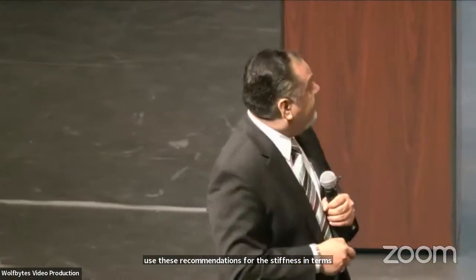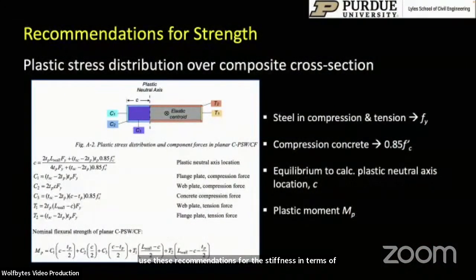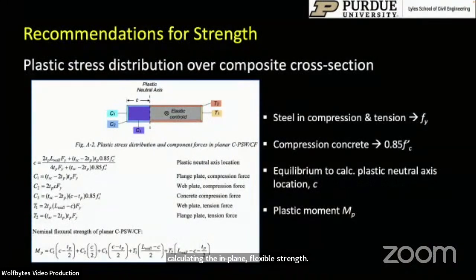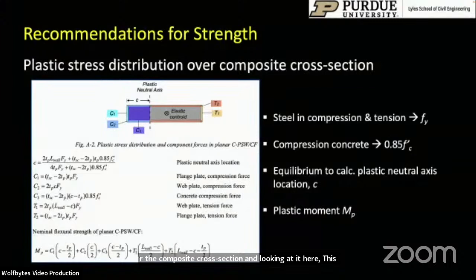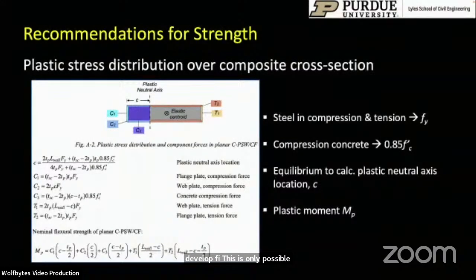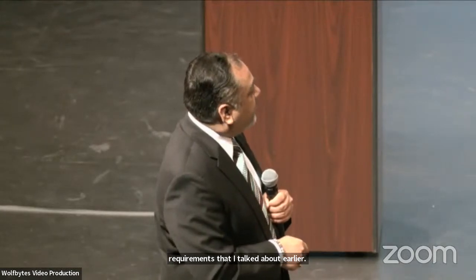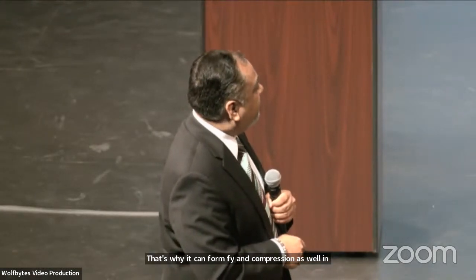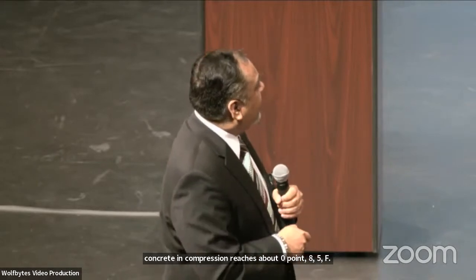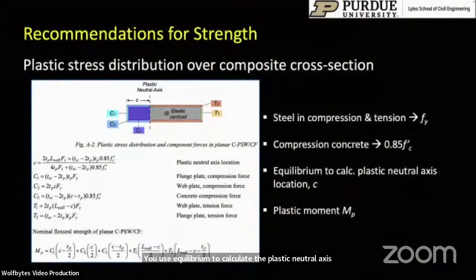In terms of calculating the in-plane flexural strength, we recommend the plastic stress distribution method over the composite cross-section. You're looking at it here. The steel in compression and in tension is assumed to develop Fy. This is only possible because in compression, we made the steel plates compact or non-slender by meeting the requirements that I talked about earlier. That's why it can form Fy in compression as well. The concrete in compression reaches about 0.85 F prime C. You use equilibrium to calculate the plastic neutral axis and then the plastic moment capacity. Equations such as this are given for multiple different composite sections in the upcoming design guide.